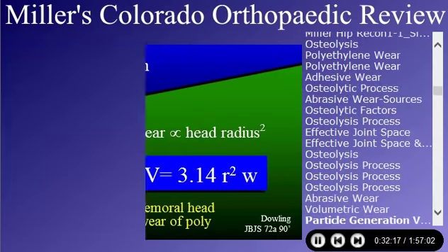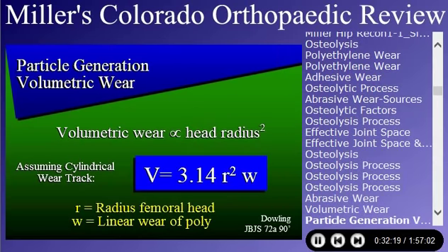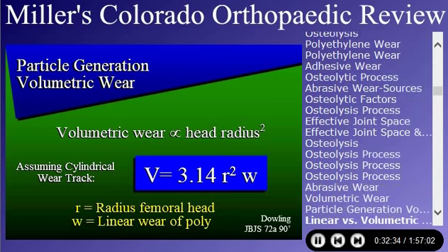The volumetric wear, if you round it off to a rough formula, is related to pi r squared times the linear wear rate, which is basically the volume of a cylinder. Just remember that it's related to the r squared. So the larger the ball, the more volumetric wear, the more particles you're going to generate. So you have this trade-off.